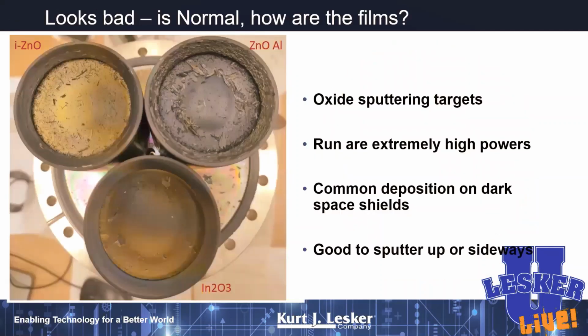Now, it doesn't mean your targets are always going to be beautiful. Here's a bunch of targets which have run successfully. They made great films, but over time they had lots of redeposition, lots of cracking and things like that. And so you just have to go in and clean this stuff off. It looks horrible, but actually these targets are in pretty good shape. They just need to be cleaned. You notice that your dark space shield here has got a lot of accumulation on it. You want to clean that off before it actually flakes off and maybe shorts out the gun.